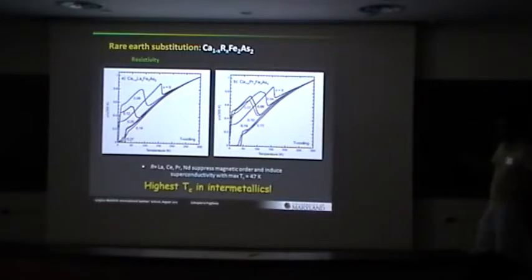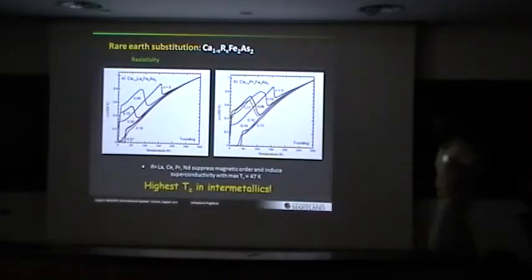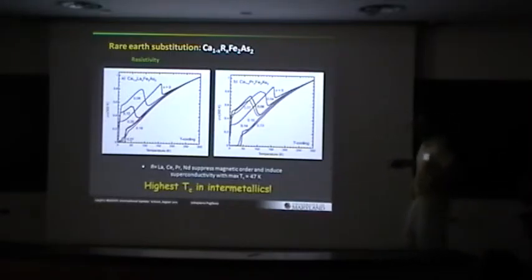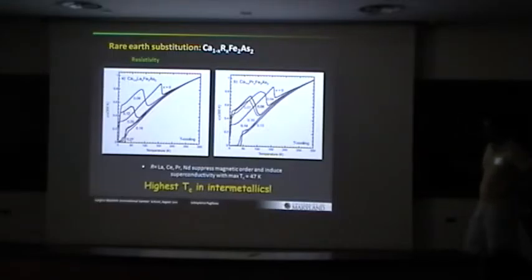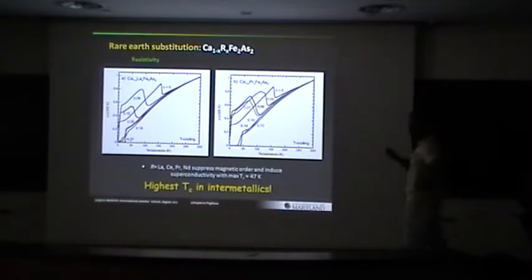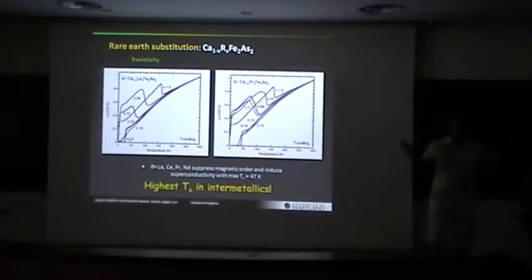Here's the resistivity, same series, lanthanum and praseodymium. Suppress the magnetic order, and here's this large upturn that I was referring to yesterday that persists. So that's quite different than the potassium substitution. And then at some concentration, you get superconductivity. So that's quite interesting. And the really weird thing is that with praseodymium, we also see superconductivity. And that's in the presence of this collapse. So this is the most anomalous result here. And there's some caveats to this.